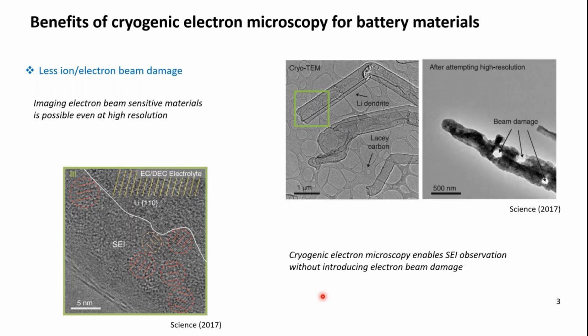Okay, here shows why cryogenic electron microscopy plays an important role in characterization of battery materials. When we attempt high-resolution imaging of SEIs, you can easily damage your samples at room temperature, but combined with air-free transfer, now we can attempt high-resolution imaging of battery interfaces at cryogenic temperatures. And as you can see in the left image, this is a significant research progress because we can image the SEI at nanometer scale and even at atomic scale while observing the features in the SEI.